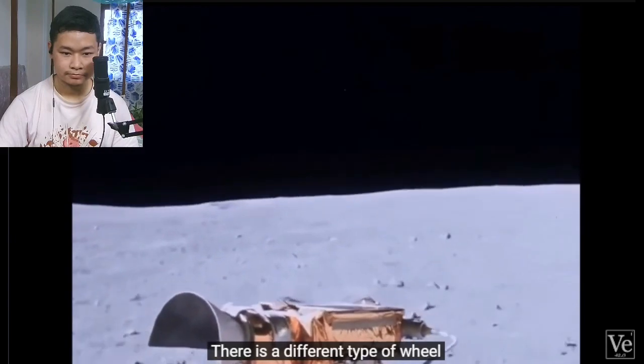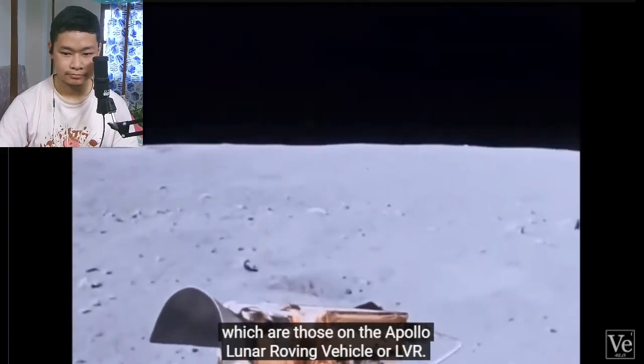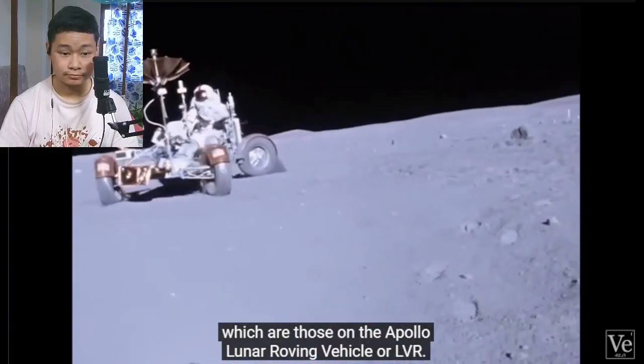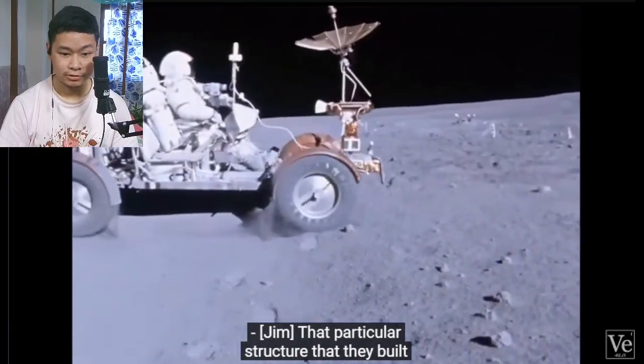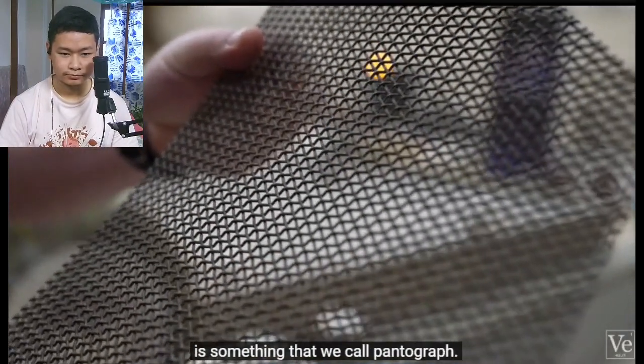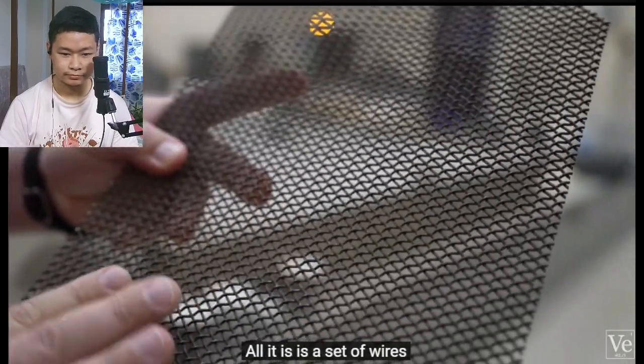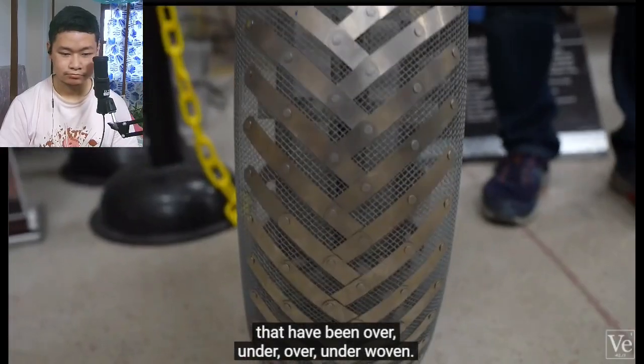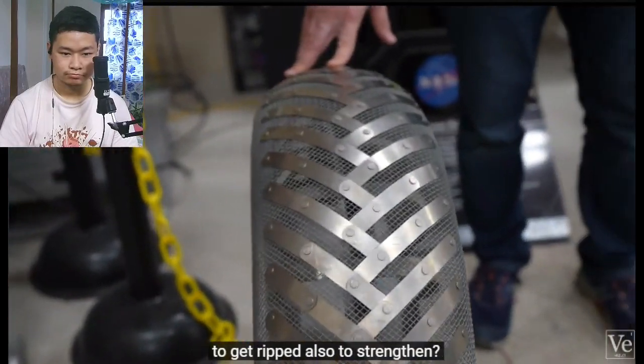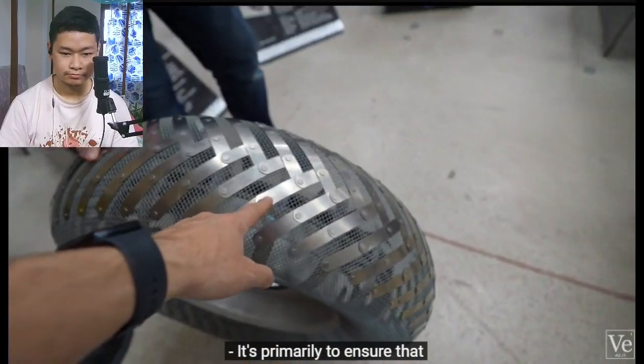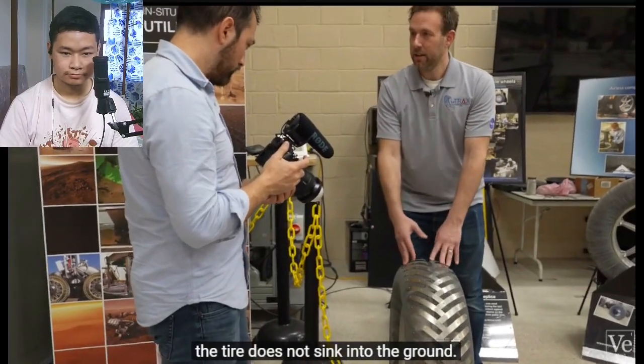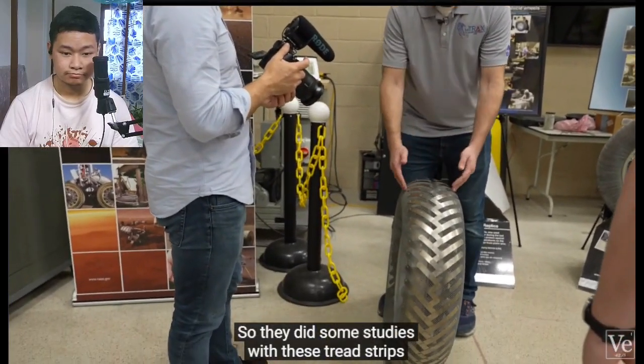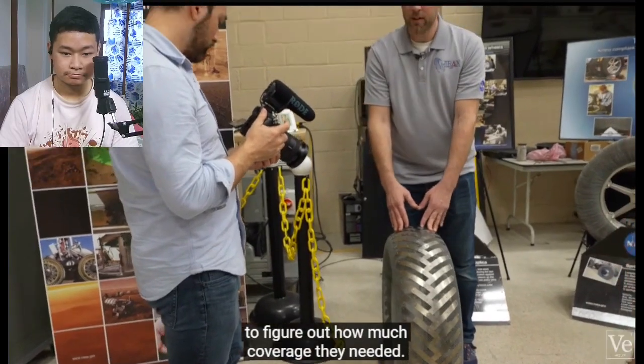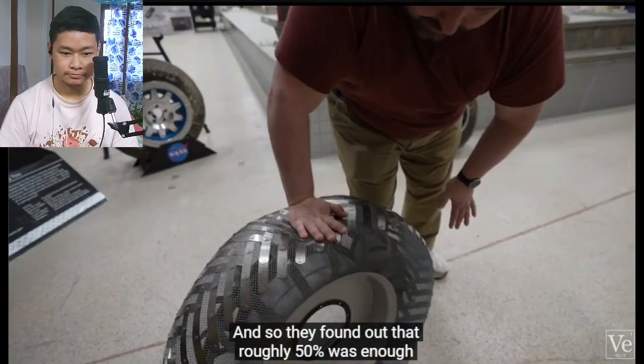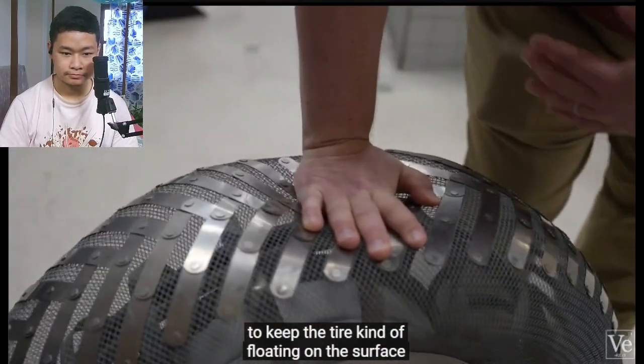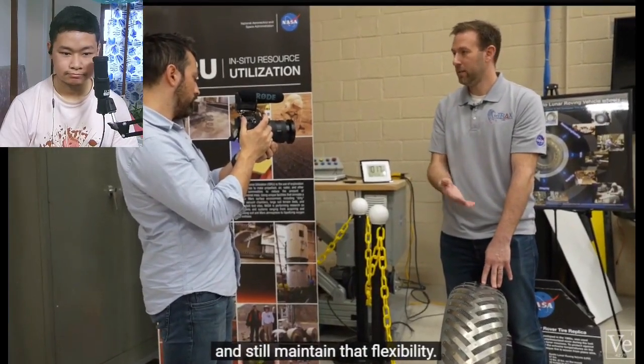There is a different type of wheel that NASA has tried in space, which are those on the Apollo Lunar Roving Vehicle, or LRV. That structure that they built is something that we call a pantograph. All it is, it's a set of wires that have been woven over and under. And this on the surface here is to get grip, also to strengthen. It's primarily to ensure that the tire does not sink into the ground. So they did some studies with these tread strips to figure out how much coverage they needed. And so they found out that roughly 50% was enough to keep the tire kind of floating on the surface and still maintain that flexibility.